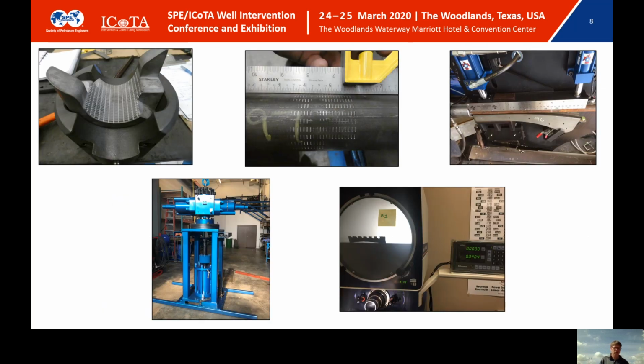So this slide just shows some pictures. The picture in the top left is a set of coil tubing slips from a BOP. It just kind of shows the serration pattern. The middle top picture shows the resulting slip mark damage after we applied the slips and pulled 100,000 pounds of tension into the coil.